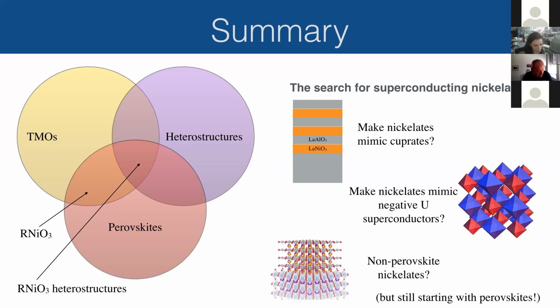Well, okay, so the other nickelates only become anti-ferromagnetic when they are already insulating. It's probably not possible for lanthanum nickelate because it never becomes insulating. There have been relatively recent studies where they synthesized single crystals of lanthanum nickelate where they find, or they claim to find, some kind of magnetic tendency, let's say. It seems now that that is mostly coming from a slight oxygen non-stoichiometry. So even in very pure crystals of lanthanum nickelate, I think that you still don't find any magnetic order. Certainly not magnetic order, and probably not any magnetic fluctuations either.